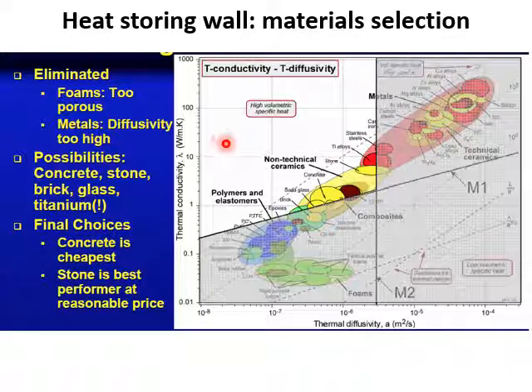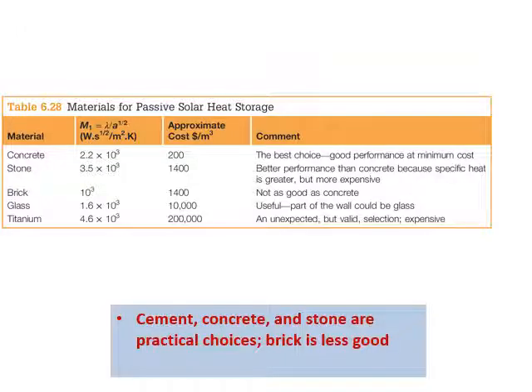So the limited ones would be the foam, which is too porous, and the metals, where the diffusivity is too high. And then the possibilities would be the concrete, stone, bricks, glass, titanium. So the final choice would be the concrete, because it's very cheap, and stone is the best performer at reasonable price. So it's kind of obvious. Although it's quite obvious, so that you can choose either concrete or stone, but you need to actually calculate the material index for each material.